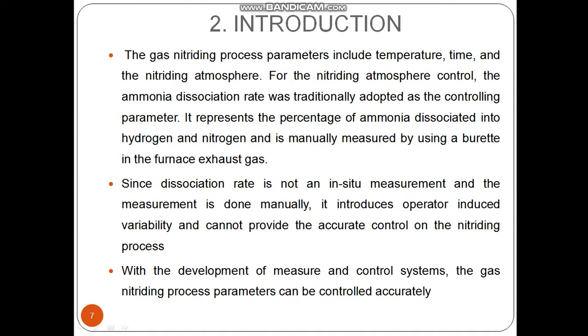For the nitriding atmosphere control, the ammonia dissociation rate was traditionally adopted as the controlling parameter. It represents the percentage of ammonia dissociated into hydrogen and nitrogen and is manually measured by using a burette in the furnace exhaust gas. Since dissociation rate is not an in situ measurement and the measurement is done manually, it introduces operator induced variability and cannot provide accurate control of the nitriding process.